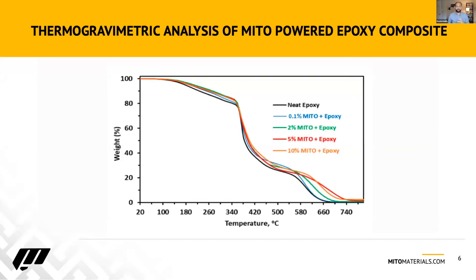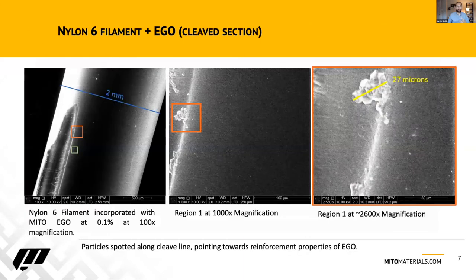And so looking at the TGA, we don't affect the thermal degradation of the polymers that we go into. We've seen this across the board, whether it's thermoplastics, thermosets, coatings, adhesives, it remains totally the same. We don't affect the curing profile, the gel time, viscosity, anything like that, because we go in at such a low concentration.